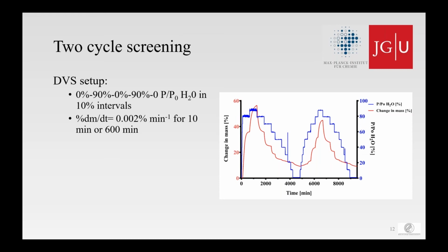A possible explanation for the data that we see here is that after the reaction, partial dissolution and recrystallization at the interparticulate interfaces took place, which resulted in a reduced total surface area that was available for water sorption in the second cycle.